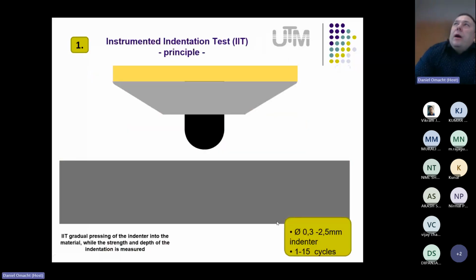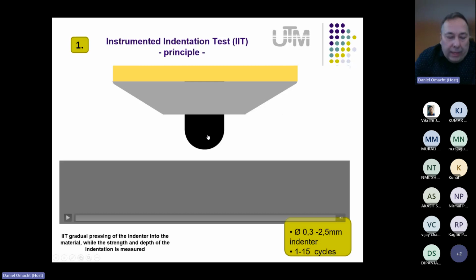As I said, the first part of this presentation is about instrumented indentation test principle. As it is visible in this picture, you can see the indentor. Indentor is in the shape of the ball, and we use indentor in the diameter from, we can say, 0.3 millimeters up to 2.5 millimeters. The principle of the testing is gradual pressing of the indentor into the material, while the force and depth is measured. For our testing or for evaluation, we use 15 cycles of the instrument indentation test.